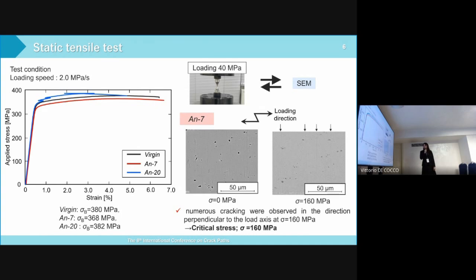Next, it is known that the anodized film is composed of almost amorphous alumina, and cracking can easily occur. The anodized film affects not only corrosion and wear resistance, but also fatigue strength. So we investigate the critical stress